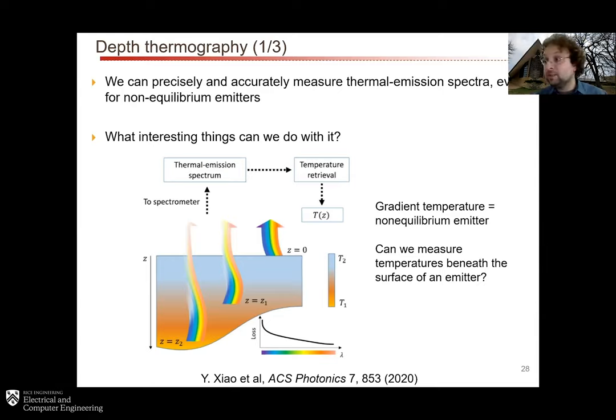In my experience, if you're doing things in the visible or near infrared, the thickness doesn't have to be that thick, but if you're going to do this in the mid-infrared, up to about 50 microns, you actually want the thickness to be something like 200-400 microns of a dense carbon nanotube forest in order for it to be really quite a bit like a black body. But that can be a little bit challenging, because carbon nanotube forests can also be a little bit uneven, can be a little bit scattering.